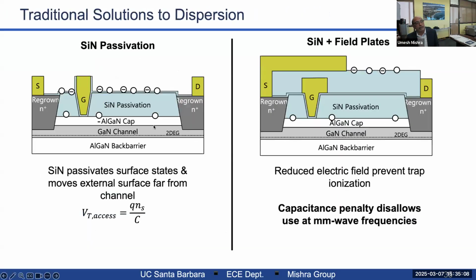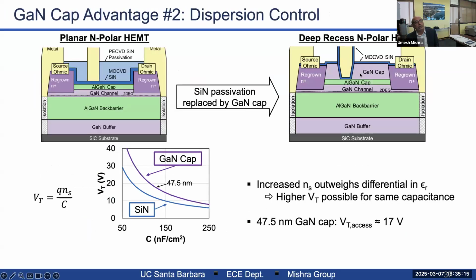Very important. Of course, you can have field plates on top. So here a typical device will be a gallium nitride channel like this. And this gallium nitride channel followed by the gallium nitride cap gives me a very high threshold voltage. What do I mean by a threshold voltage? The surface has been moved away. So if an electron gets on the surface, the electron on the surface cannot deplete the electron in the channel easily because the capacitance has been decreased. So the threshold voltage of the region in the cap is much higher than the region underneath. And that's basically the threshold voltage of the access region.